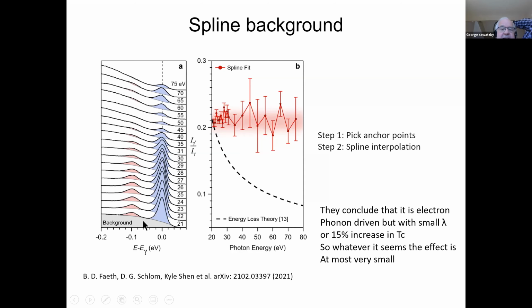Now, the problem with that is that there is another peak in between here. Yeah, there is another peak. That's a 60 millivolt peak. And if you change that spline background in that region just a little bit, then the intensity of this one will immediately increase by a lot. This spline always has to be a bit lower than what the experimental data shows because of the overlapping tails of these states that you have. So it really isn't correct to do this.